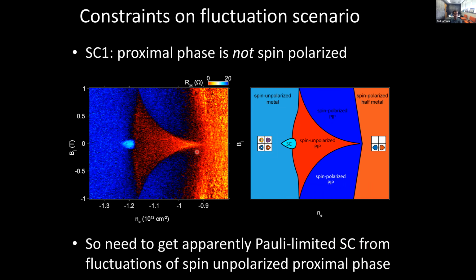There are some constraints. This is maybe a little bit for the experts, in particular those who are into the details of these graphene systems. But one thing we know about the phase proximal to the first superconductor is that it is not a spin polarized phase. So the transition is between a spin unpolarized metal and some kind of spin unpolarized ferromagnet. It may be something perhaps where it develops spontaneous coherence between the two valleys, and there's later a transition to a spin polarized set of phases.